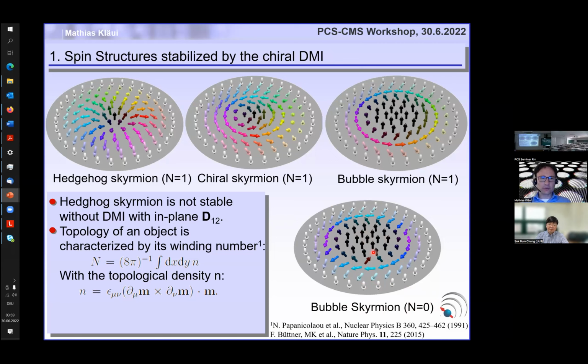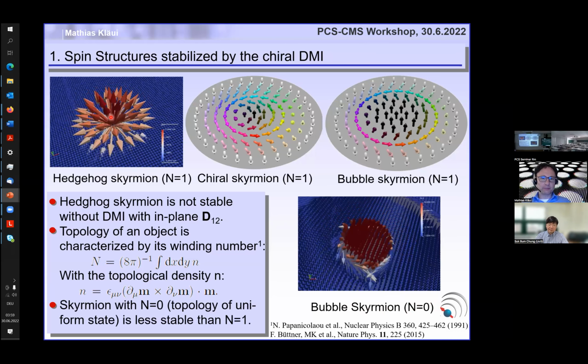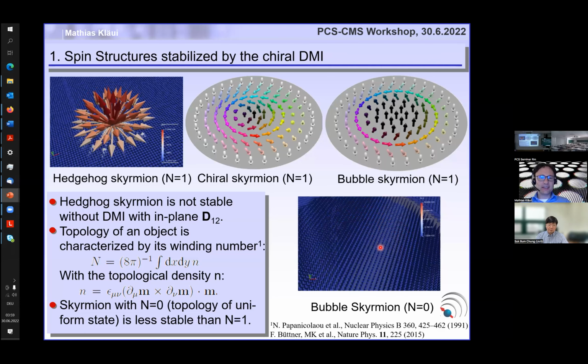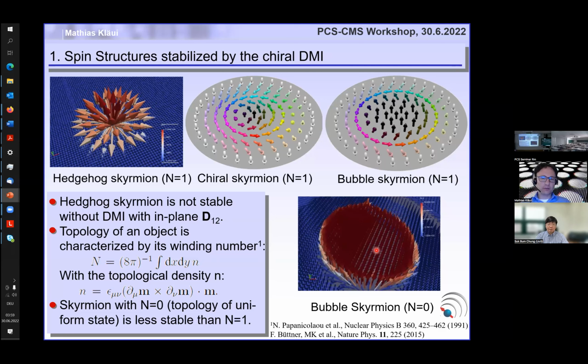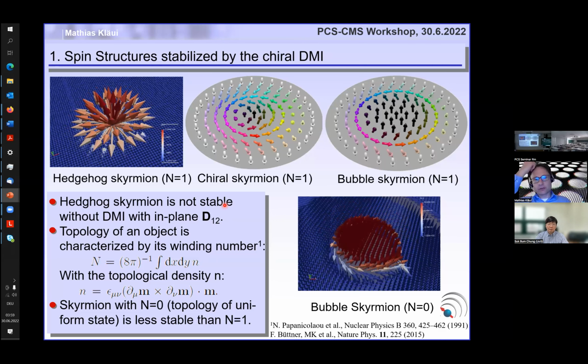And I can show you also how. So if you apply a small field to destroy the Skyrmion, this Skyrmion here will simply shrink a little bit, but be stable. But this Skyrmion here, with just a little bit of field, it can continuously rotate to annihilate, and therefore we completely annihilate the spin structure, forming the uniformly magnetized state without changing topology. So that's the importance of topology.